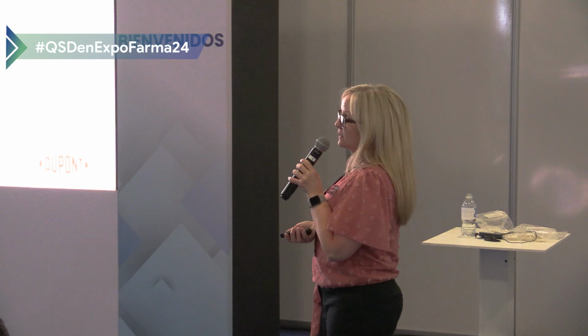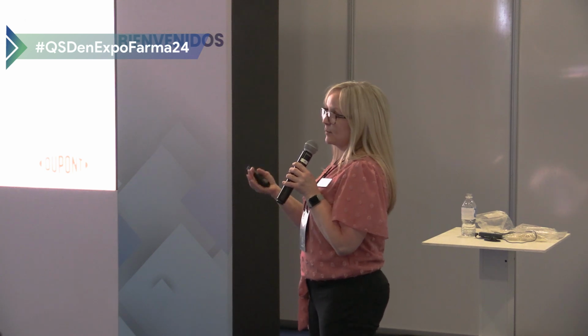So this shows during our processing, usually in a development lab like I do, or in some sort of laboratory, we mix those two bottles of material at a 1-to-1 ratio, and then we put it in like a vacuum oven to remove the air so there's no bubbles, and then you use a drawdown bar to put it onto a substrate, and then cure it in an oven at usually 130 C is what we recommend.